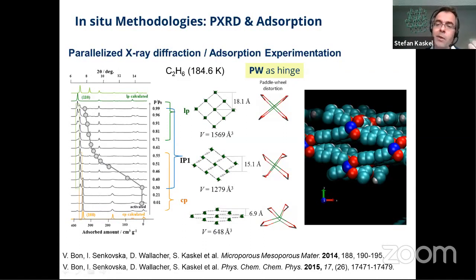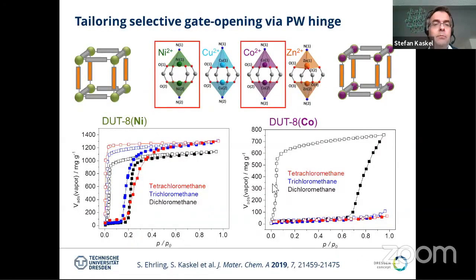And this then shows you very easily, or makes you rationalize, how can I tune the behavior of this type of material? I need to tune the hinge, and the hinge energetics can be tuned by changing the paddle wheel composition, for example, by introducing other metals. The original MOF that we developed was a nickel MOF with the nickel paddle wheel, and we have now all the other metals, of course, and I would like to highlight the behavior of the cobalt system, a work recently published by Sebastian Ehrling, one of my PhD students.